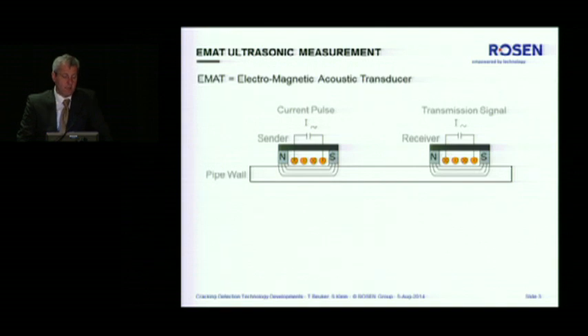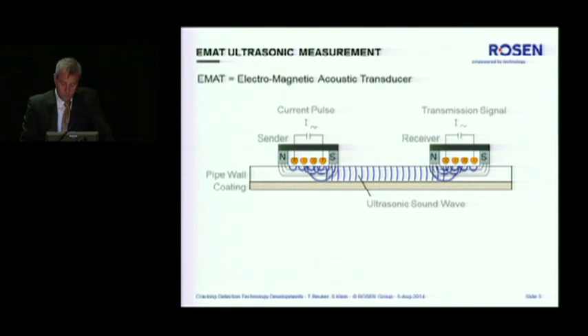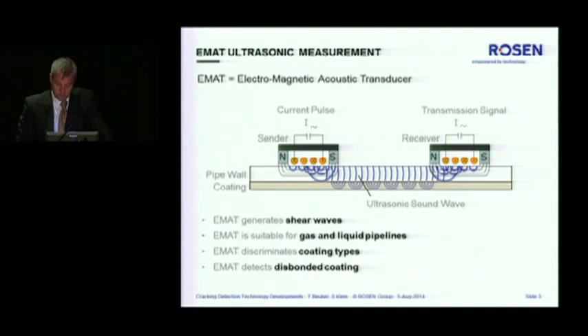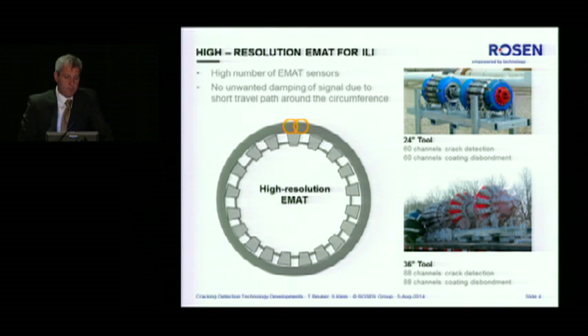So how is the EMAT technology working? We have a coil system with magnets. This is called the EMAT transducer, and the receiver looks similar. In an electromagnetic way, an ultrasonic wave is coupled into the material. It's a shear wave, and since it's electromagnetic, no liquid coupling is required between the device and the pipe wall. Now, if you have a coating on the pipe, some of the energy dissipates into the coating, attenuating the signal. This needs to be taken into account later, but an advantage can also be taken out of this, and coating disbondment and coating types can be detected and characterized. So the way the EMAT is implemented, it's a high-resolution approach.